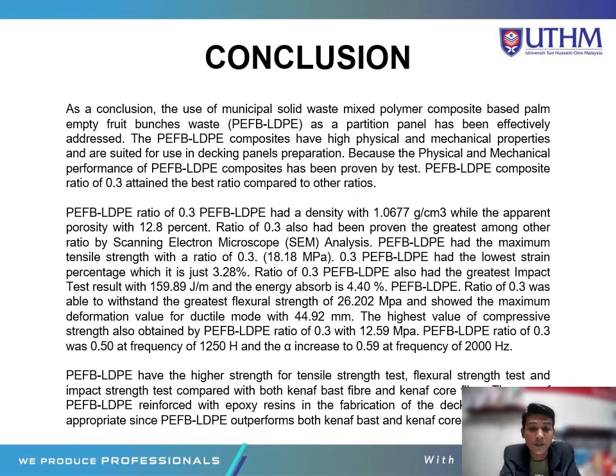PEFB LDPE ratio 0.3 was able to withstand the greatest flexural strength of 26.202 MPa and showed the maximum deformation value for ductile mode with 44.92 mm. The highest value of compressive strength was also obtained by 0.3 with 12.59 MPa. For PEFB ratio 0.3, the sound absorption alpha was 0.50 at the frequency of 1250 Hz and the alpha increased to 0.59 at the frequency of 2000 Hz.